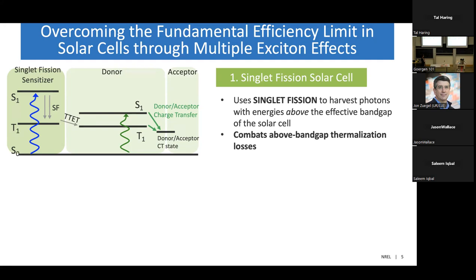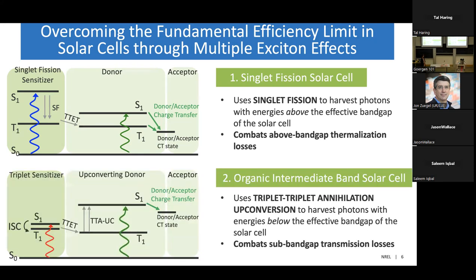So it absorbs blue light, produces triplets that are then transmitted into the main solar cell for dissociation. And if we take a look at the green photons that this normal solar cell is able to absorb, by adding this singlet fission sensitizer, we're also able to take advantage of some high energy blue photons that previously would have been thermalized, right? So the singlet fission solar cell gives us a way of combating these above band gap thermalization losses. The next type of solar cell is an organic intermediate band solar cell.